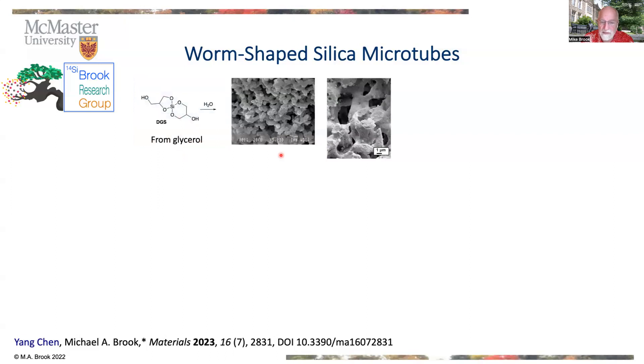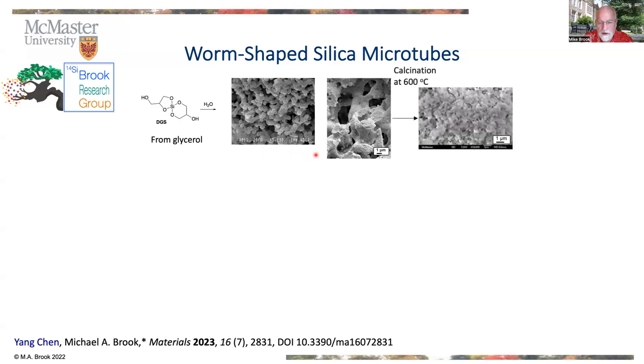Well, synthetic chemistry is doing the same game too. We found that you could take this glycerol-derived silicone under hydrolysis conditions — sol-gel chemistry — to make not quite as beautiful as nature, but these very open structures that arise because of the way in which the sol-gel chemistry takes place with glycerol. You can see a zoom in here to see there's much more structure.